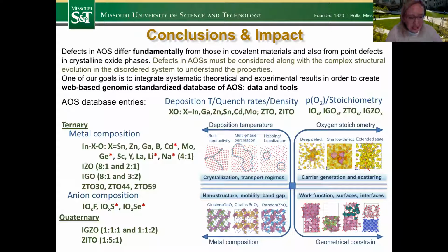Thank you, that's a great question. Yes, of course it's hard to see on such a level. What we looked at is actually the optical response and optical properties. And we do see in the IR spectrum the enhancement in the absorption near the peak. So we identify that indeed, because of the lower scattering when we have the chains, we are seeing it optically. Otherwise, the structure is very hard to resolve and identify. And if I'm showing the chains in a small structure, in a real sample they are all interconnected, right? There is no direction to this chain. So that's why it's essentially impossible to identify these with traditional methods.